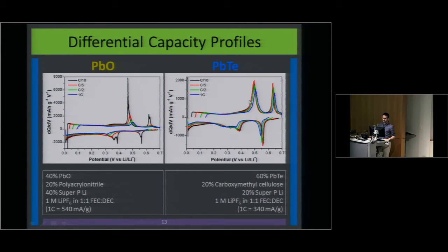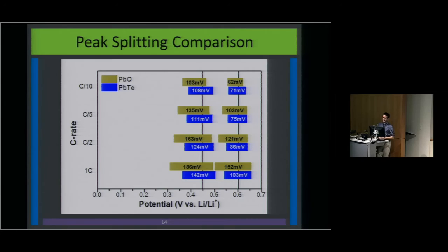So if we put little bars here, where the left side of the bar represents the bottom peak and the right side represents the top peak, we get a graph like this. I think this makes it more clear which of these materials is actually winning the competition. The lead oxide starts out relatively small, but as you increase to not even that high of a rate, 1C, the difference between the peaks gets much larger.